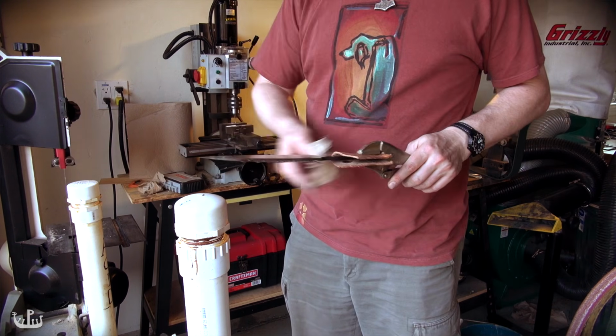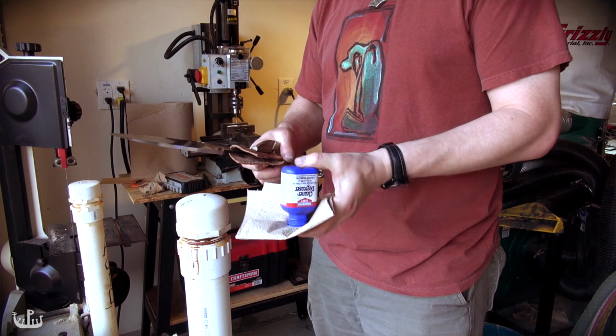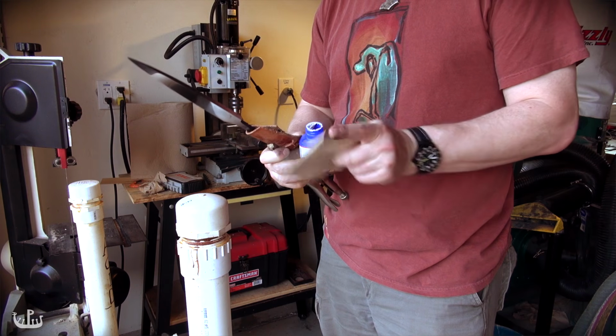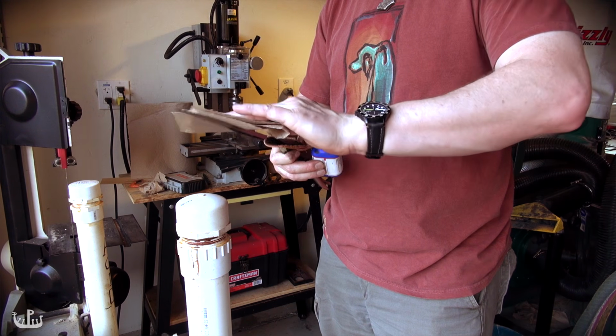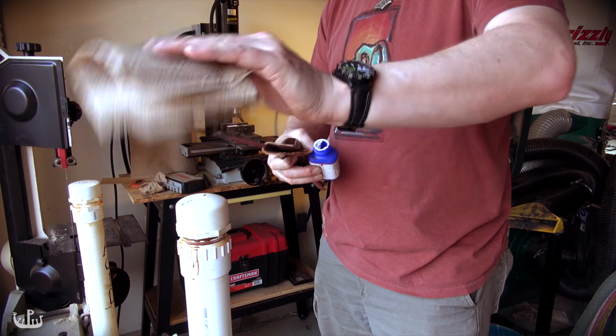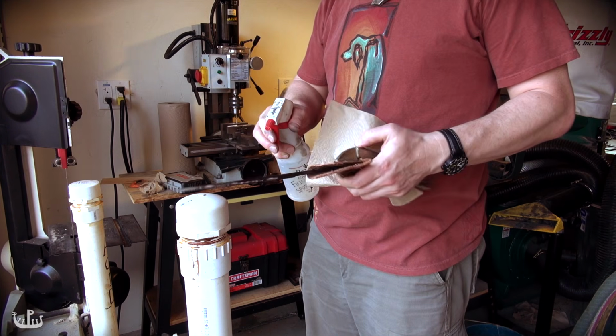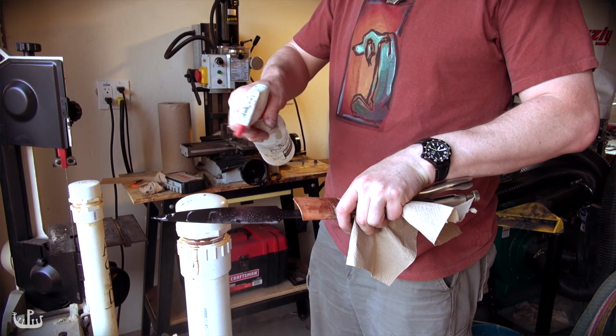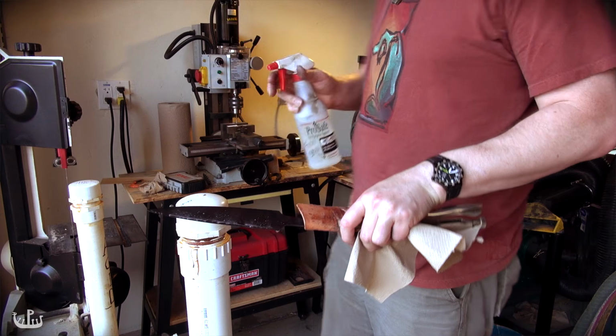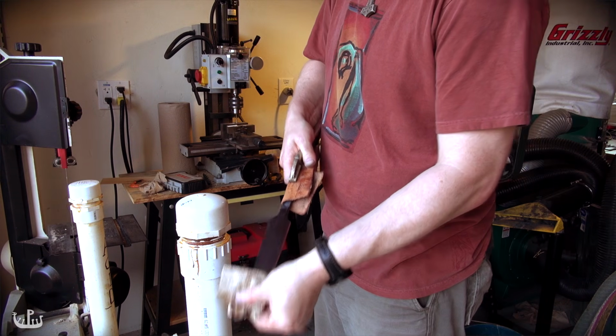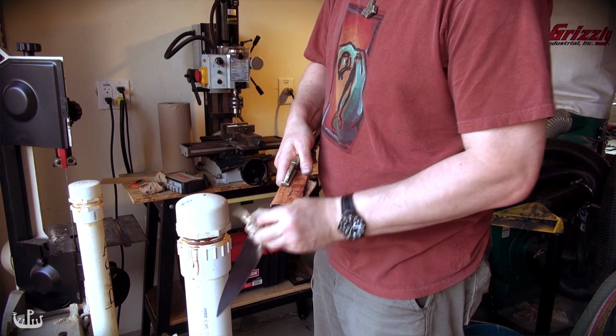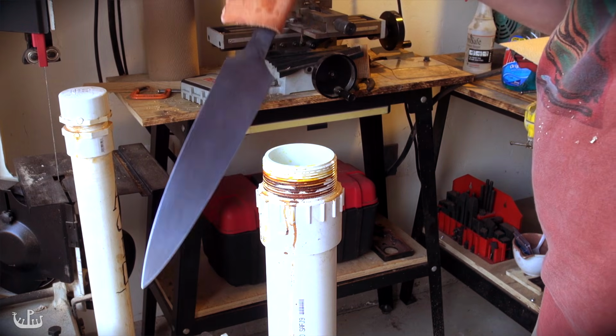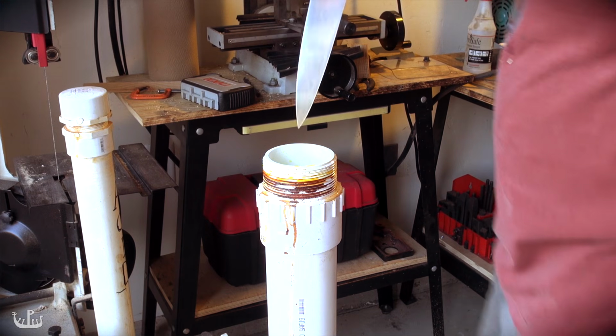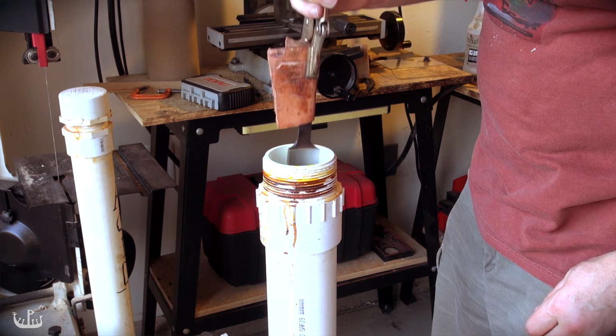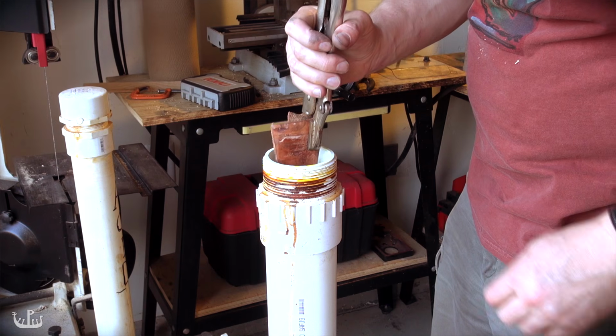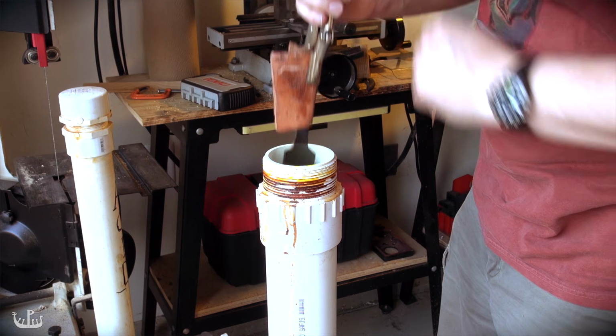To achieve the uniform edge, it is important to remove all oils from the blade. I do this by thoroughly cleaning it. For pattern welded blades, I might etch up to 10 or 20 minutes. For the Crucible steel, I dip the blade in only for about 30 seconds.